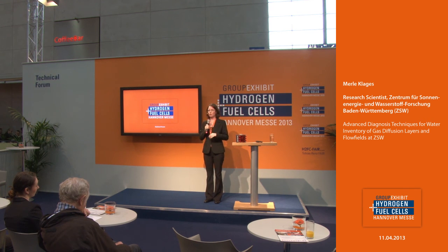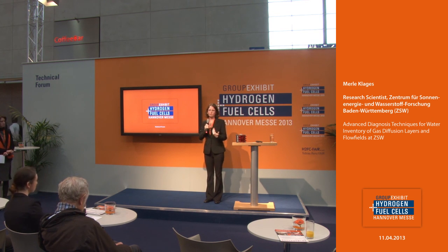We performed different Monte Carlo simulations at different times of degradation, and this is one study we did to change the properties. But you could also change, for example, the porosity. And as the input into the simulation was the actual tomography of the fibers, you can also take fibers which are thinner or thicker. We can also simulate that, yeah.